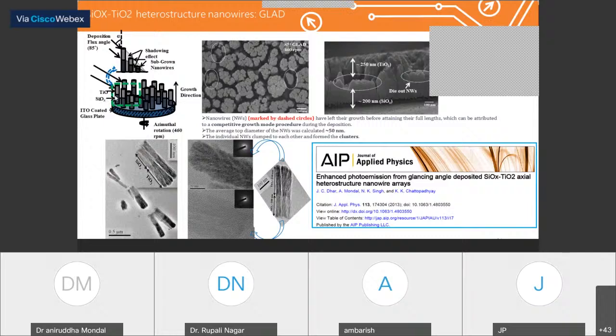The silicon monoxide and titanium dioxide heterostructure nanowire-based photodetector has also been fabricated. In this case, you can see we first deposited the silicon monoxide beneath, and on top of that the titanium dioxide nanowires have been fabricated by glancing angle deposition techniques. This is the TEM image. You can see the fabrication of the SiOx and titanium dioxide nanowires from the color contrast. And we have seen this kind of nanowire is very, very important.